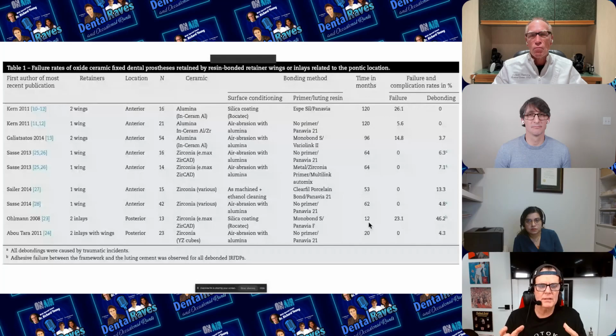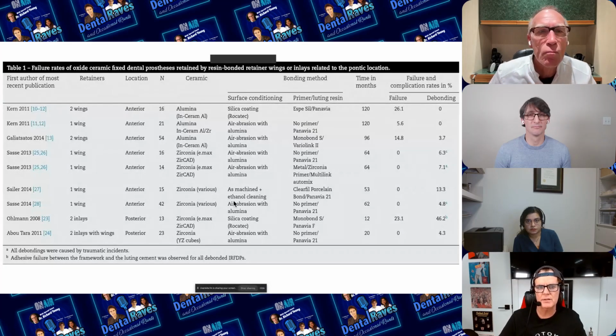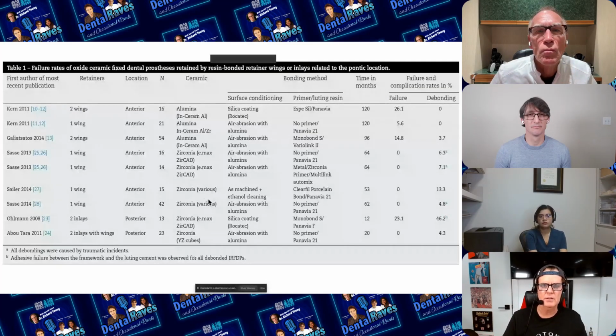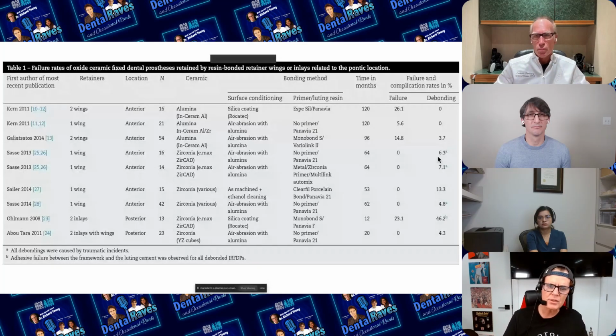So what that basically tells us, and they've all followed protocols that we all know, everything was either sandblasted or Rocatec, is that the variability is extremely high among the studies. You have one author that had zero failures, so maybe he's got the technique down, and maybe if we looked at his preparations, he put some more macro-mechanical retention in. What we see is we don't see this kind of failure with etched ceramics. It just doesn't happen. The reported failure rates are 1-2% maybe, if that. Fracture, that's a different issue. So really, here's what's happening. We might as well go into this right here.